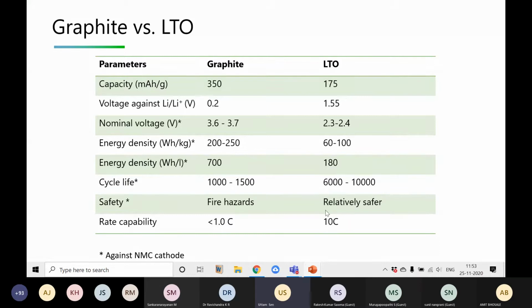So you can charge and discharge the cell at 10C rate. Whereas in case of graphite, we can charge or discharge less. I mean, charge we can't do at 1C. It has to be less than 1C. But discharge you can go higher, even 1C is okay. But in case of LTO, 10C charge and 10C discharge it can support. Okay, 10C means it will charge in 6 minutes.